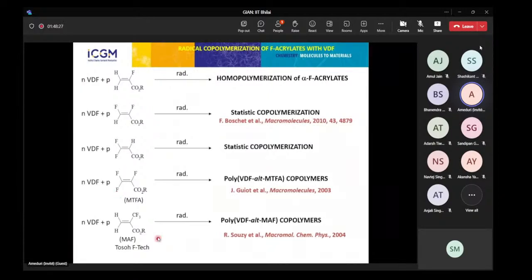So you can see that you have different acrylates copolymerized in the same conditions. And indeed, when you do this reaction, this alpha fluoroacrylate is so reactive that it doesn't go to copolymers. It reacts on itself by making a homopolymerization. And then when you consume it all, you can add some VDF. So we decided to soften its reactivity, to make it slower, by adding a fluorine here. So we synthesized it, of course, by organic chemistry. And in this case, we have some statistical polymerization. So it was possible to tune the good conditions in order to have a good PVDF, let's say with 10% or 5% of this, in order to satisfy some properties.